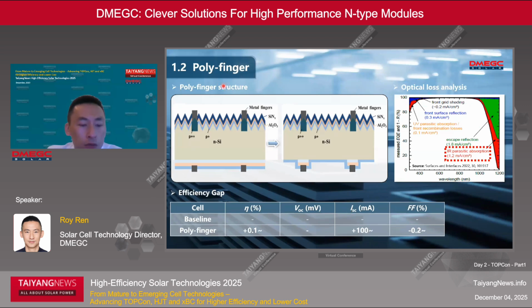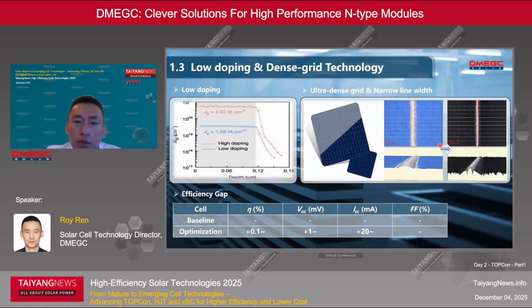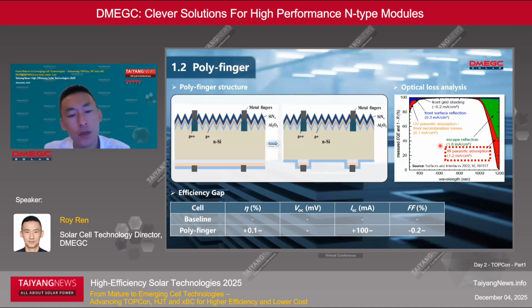The polyfinger structure removes the polysilicon in areas without grid lines by etching. We know that polysilicon has serious parasitic absorption. Thus, with this cell structure, we can achieve an efficiency improvement of over 0.1%, especially with a significant enhancement in short circuit current. However, we also have observed effects on fill factor due to the increased difficulty for carrier transport.